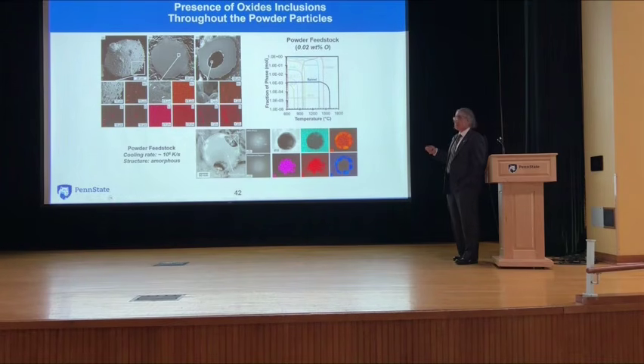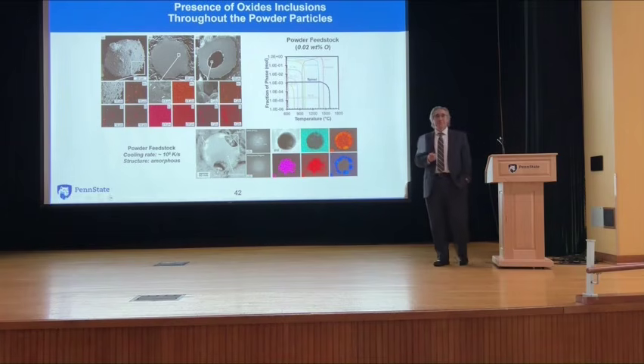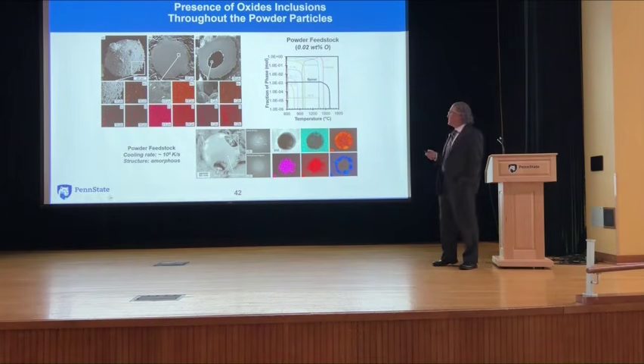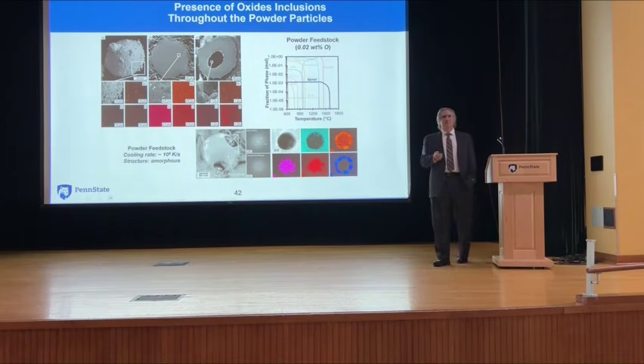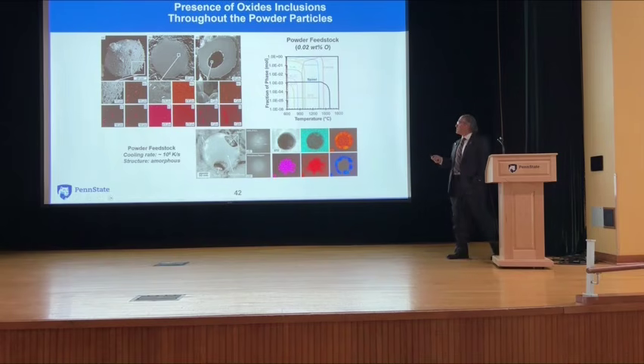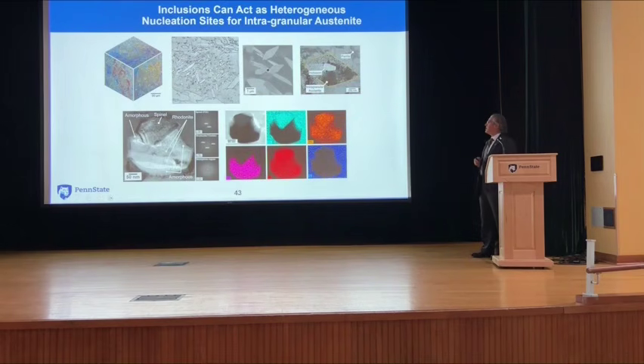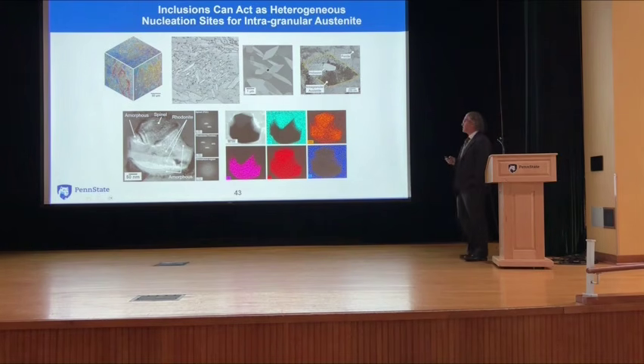This is a cross-section of a single powder particle. It shows up in there too. And when we started really looking at it, it actually shows up as amorphous because of the rapid cooling rates of the powders as we produce them. And they will develop as you start increasing the heat treatment of it. So if you start hot isostatically pressing it, you start doing all these things.